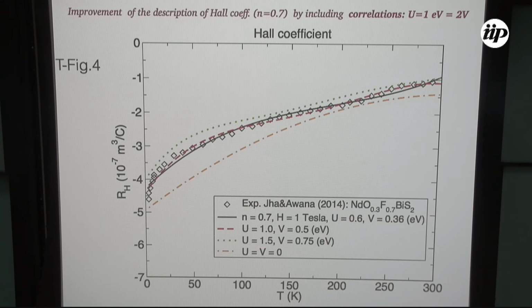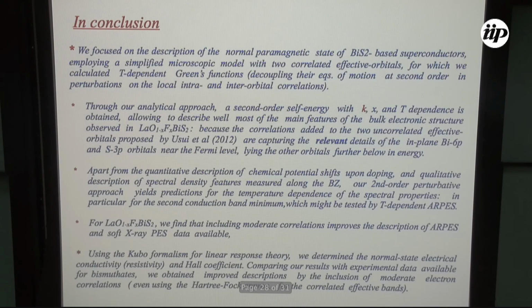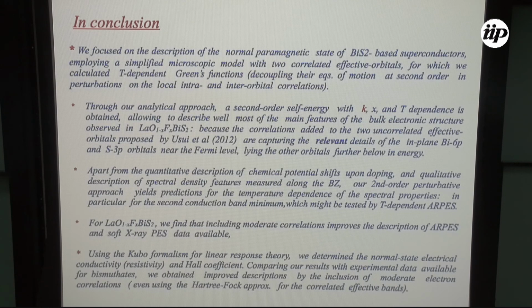This is something I would like to talk about with some of the people here in the audience who are experts in Hall coefficient and Hall measurements. But we believe it has to do with the multi-band character of the electrons intervening in the transport. Basically, here are my conclusions: with our approach, looking at this compound, the one with the optimal high TC in these materials, we could get a quite reasonable description of the spectral properties and even the first transport properties we are looking at.